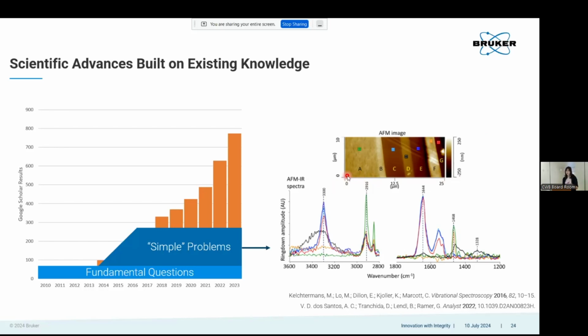And so with this, we're able to reverse engineer what this material is made of by looking at that infrared fingerprint. So we can see some areas are made of polyethylene, this A area, just by looking at the spectrum here. We can see the C and E, which are polyamide, which affect the air permeability of the material. And then you have these other layers like D, which is an ethylene vinyl alcohol, which is a tie layer, which allows the material to be compatible with itself. So you're able to break out all these things, but this is still very fundamentally a simple problem. These things are very well segregated. You can see where the individual layers are visually using the AFM before you decide to take your spectrum.